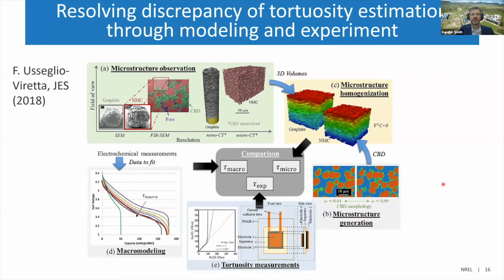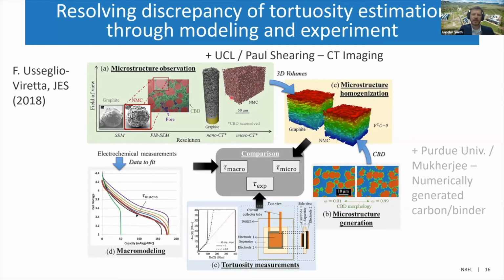So there's a lot of different discrepancy in what is the correct tortuosity for a given electrode, what type of microstructure, what are the microstructural influences. And so we did some work with 3 different methods. So here we have CT images from Paul Shearing at University College of London and his group. Unfortunately, those images do not include the carbon binder domain. You can do fib-SEM and resolve the carbon binder domain, which is what shows up in these green pockets between the red active material particles.